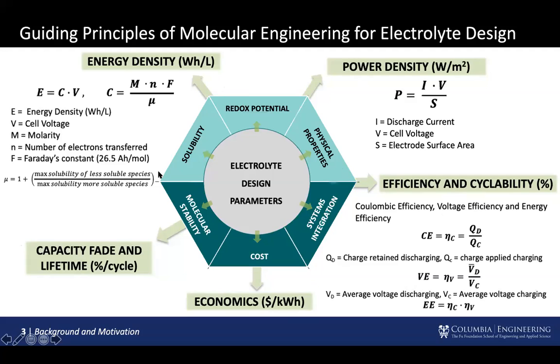And what I'm trying to get across here is that all these top level key performance parameters are related to some inherent electrolyte properties of those electrolytes in the tanks we talked about. So what do I mean by that? For example, if we look at the energy density here, this is related, as we see, to the V cell, which I talked about previously, which is related to the redox potential of those active species, as well as the solubility of those redox active species in the electrolyte. So those are the two electrolyte parameters that we want to boost in order to increase energy density.